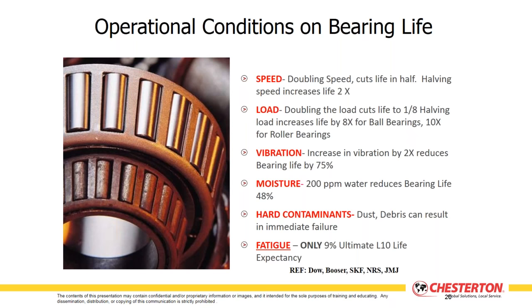Now, the interesting thing is you cannot see 200 ppm of water. Water is visible in your hydraulic oil or bearing oil at around 1,000 parts per million. So you cannot see dissolved water unless you send it out for testing and get a Karl Fischer done on it. And even then, some of your go, no-go points are set at 700 ppm. But at 200 ppm, 50% reduction in theoretical bearing life.